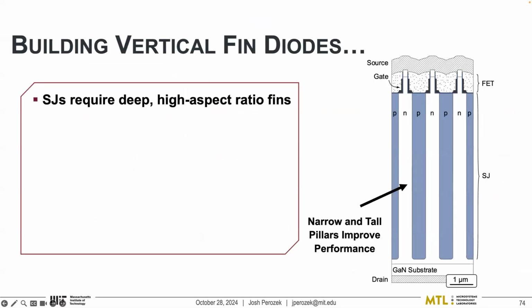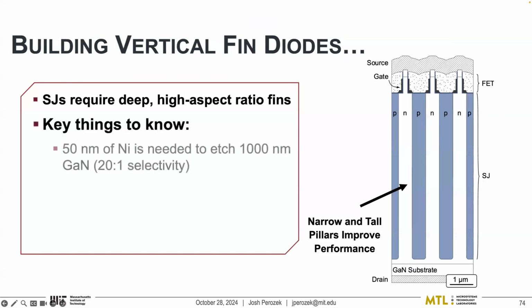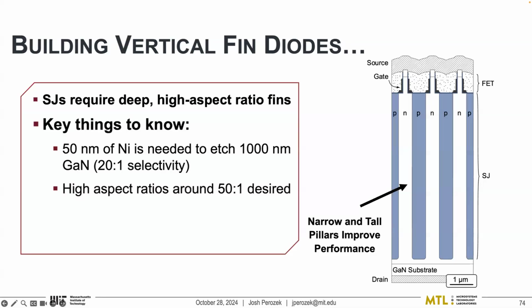The question is, how do we make this? These devices require very deep, high aspect ratio fins. Some key things to know around gallium nitride fabrication is all of our etching is done with a nickel mask. Nickel has about a 20-to-1 selectivity to gallium nitride. And for these fins, though, we want aspect ratios about 50-to-1. That means that any nickel that we pattern is going to be extremely tall and extremely narrow.